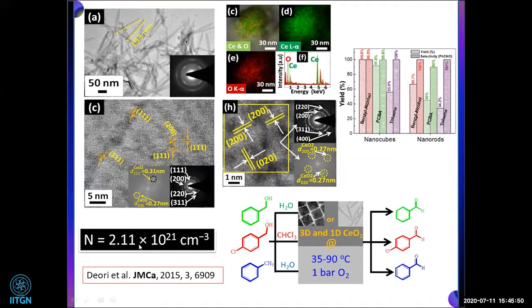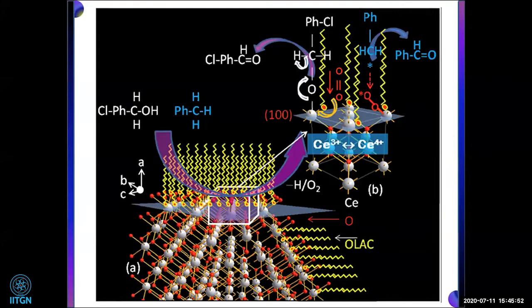After this, I want to show the mechanism. Again, as I said, there are two main points. One is the surface defect, the oxygen vacancy that is in the 100 plane. This is the 100 plane, and the other is the facet direction, right? Because this is the 100 low index facet, which gives a larger number of oxygen vacancy defects because of the lower energy. So what happened here?